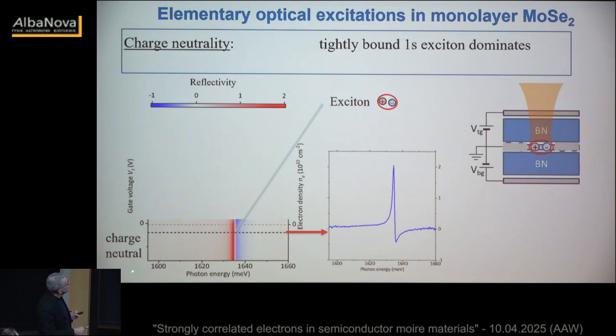All right, this is then how things look. This is the gate voltage. For a certain gate voltage range, the semiconductor is charge neutral. There are no charges injected because of the low voltage that is applied. The chemical potential is inside the gap. Then when you tune your light source, you see this resonance. If I take a line cut, you see that it has this dispersive line shape. This is our excitonic resonance. Okay? This is not the best. The peak reflection here is 2%. The best we can get by suppressing background reflection is 40%. But that's not really so important.